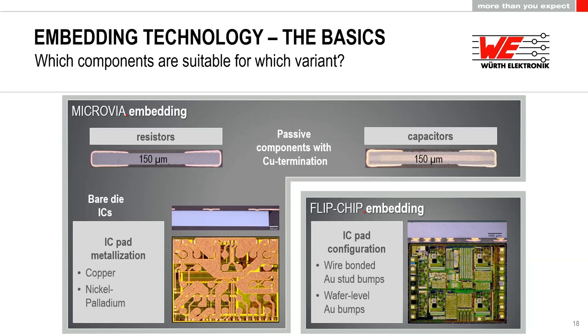For the flip chip process we are using in our process, we always need gold bumps. And these gold bumps are either made on a wafer level process already by the semiconductor manufacturer, by plating those gold bumps. This is often the case, for example, when you want to use RFID or NFC dies, which are often already delivered in this configuration. Or if you have a standard wire bond chip, we can go to our in-house wire bond process, and in the ball wedge process, we can place a ball onto the pad and rip off the wire, and then you have a gold bump as well on the pad. Then we can use our ACA flip chip process and place it onto an inner layer core.